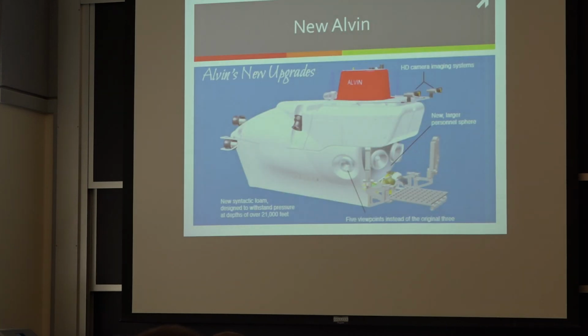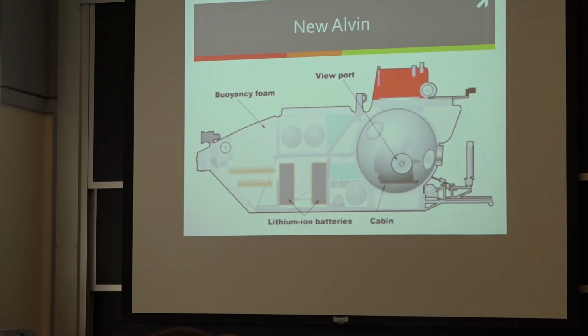So the Alvin got upgrades. Before, it just sank to the bottom, and depending on how much ballast you had, that's where you went at that level, okay? The new Alvin actually has self-buoyancy, so it can stop on its way down, do things, and then go deeper. It has new syntactic foam. I'll talk about what that is. It has 5 ports, and so it's ergonomically better. And we did determine we could build a titanium sphere. At least we thought we could do it. It has a lithium-ion battery, so it's just like your Samsung Galaxy 7 that blows up everything.